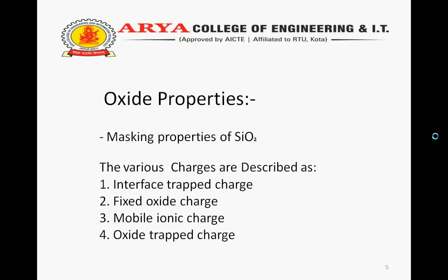SiO2 provides a selective mask against the diffusion of dopant atoms at elevated temperature. During the high temperature driven step, diffusion in oxide is slow with respect to diffusion in silicon. The thickness of oxide is determined at a particular temperature and time. This oxide thickness is necessary to prevent inversion of a lightly doped silicon substrate of opposite conductivity. A safety factor is added to this value. Typical oxide thickness is 0.5 to 0.7 micrometer.